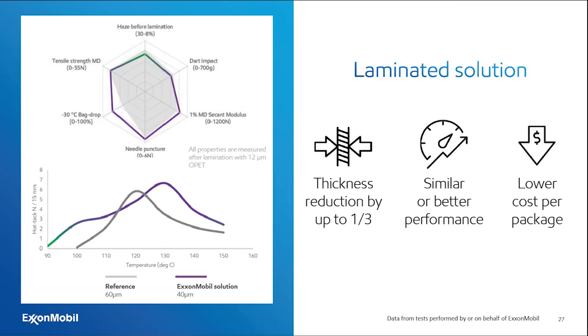And if we go to the next slide, it's the very same graph, but for a laminated solution. The difference here is, in fact, that the two polyethylene parts have been laminated together with the 12 micron PET substrate. So the mechanical data as well as the sealing performance are now measured with a substrate on top. And you see that the difference is much smaller, and that comes from the fact that once something is laminated, the substrate dictates to a large extent the mechanical performance. So you see that now the performance is pretty much the same, except for the minus 30 backdrop test. And also you see that the difference in sealing is less significant. But again, it is proven that you can do significant downgauging of the polyethylene part also in a laminate.